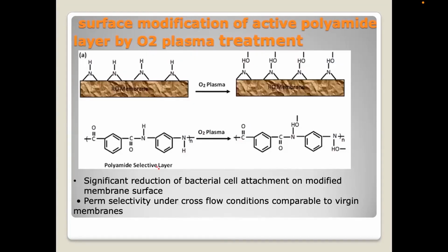Surface modification of the active polyamide. This means plasma increased the active sites in the RO membrane. The RO membrane was exposed to oxygen plasma, giving more active sites to prevent foulant and increase the lifetime of the membrane. There was a significant reduction of bacterial cell attachment on the modified membrane surface, with selectivity under cross-flow conditions comparable to the virgin membrane.